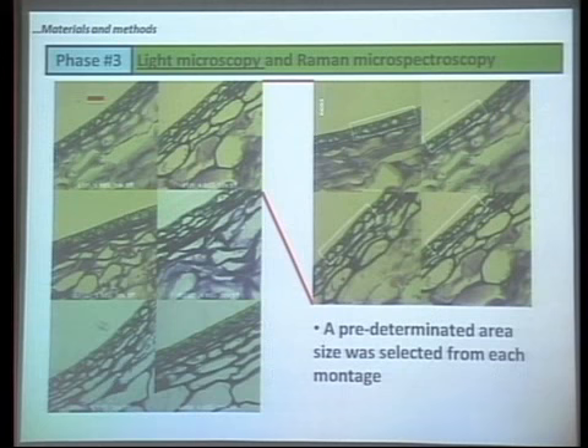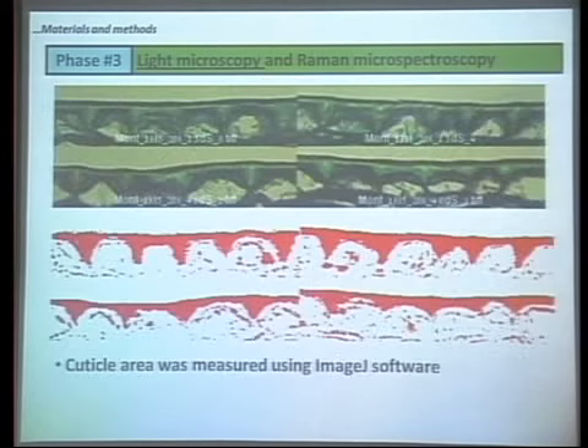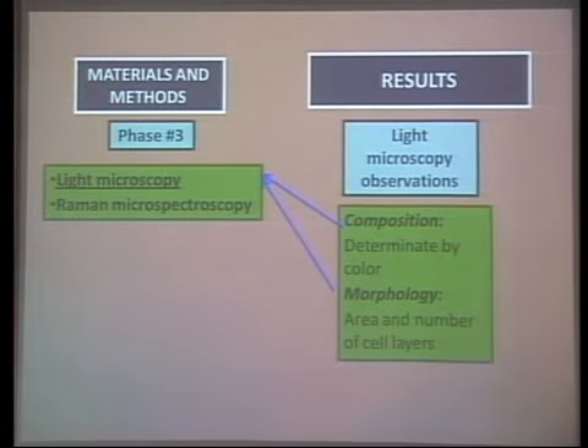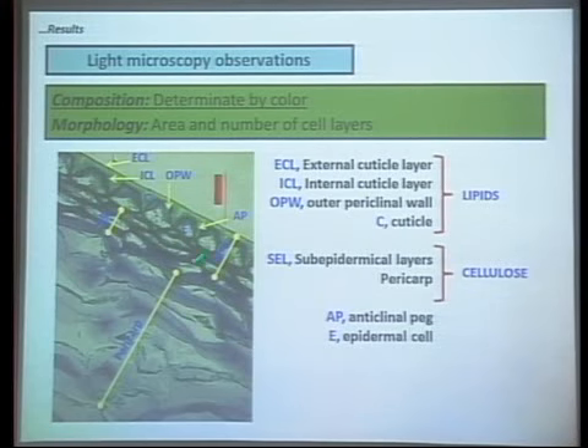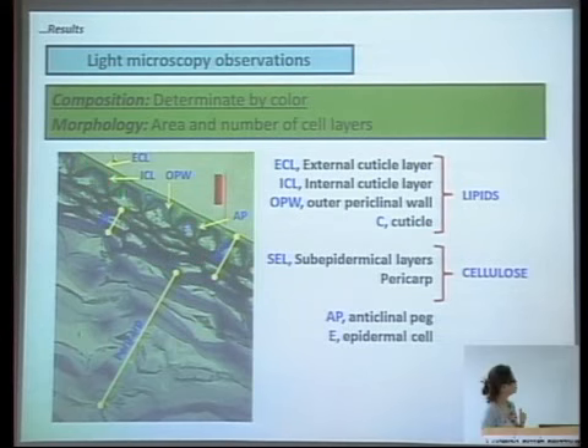So once we had our montages, we fixed an area, and then with ImageJ, we measured the cuticle area only, meaning the green part here. And the results that we got with light microscopy was as follows. Okay, so methylene blue stains green for lipids. We can see here a cuticle. We have an external cuticle layer. Then we had an internal cuticle layer.